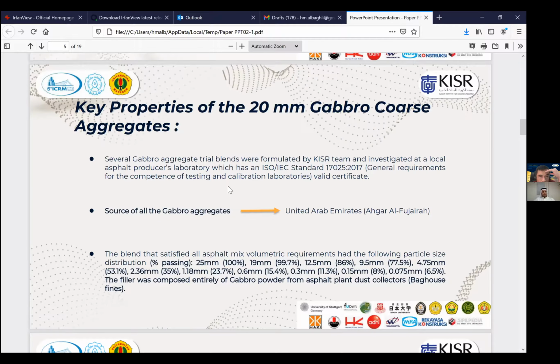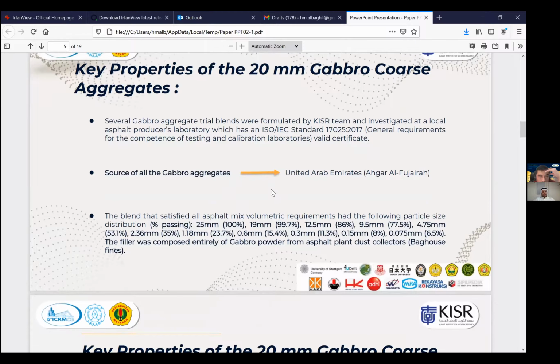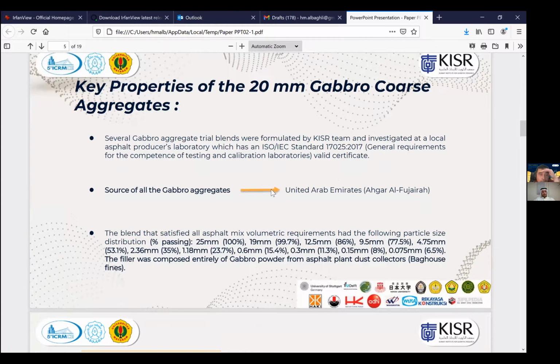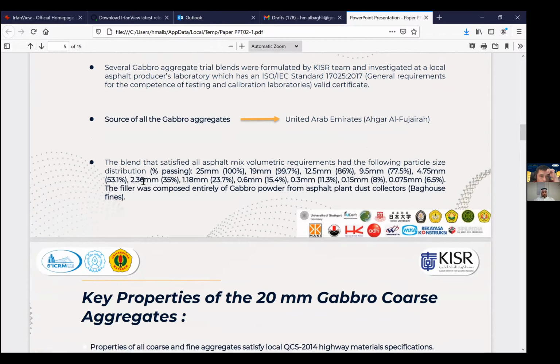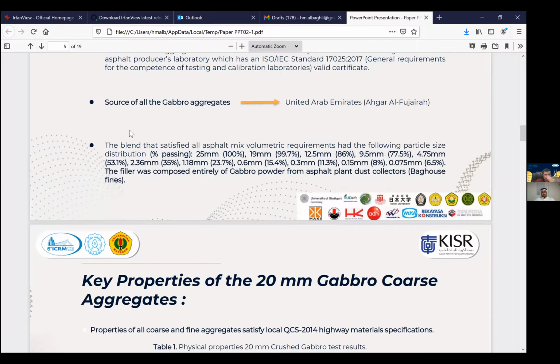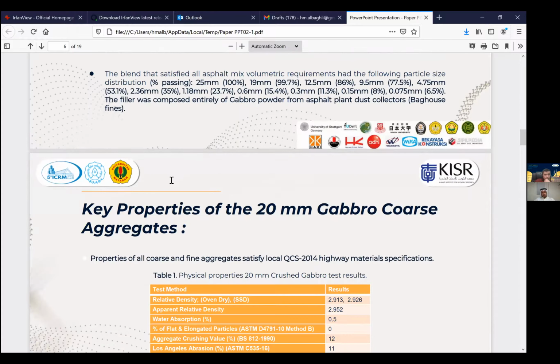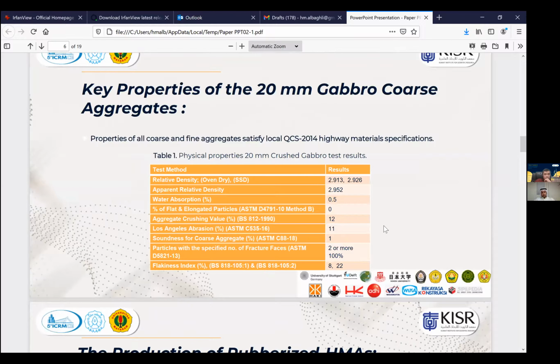For each of the trial asphalt mix blends, we analyzed key properties such as the aggregate effective and bulk specific gravities, volume of absorbed binder, and voids in mineral aggregates. The blend that satisfied all the asphalt mix volumetric requirements had this particle size distribution, as you can see. These are the properties of the coarse aggregate we used, in this table.